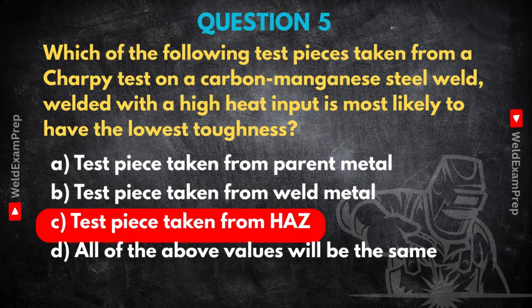The parent metal, away from the weld, keeps its original properties, more or less. And the weld metal itself, if the procedure and consumables are right, might be okay. But that HAZ is often the weakest link toughness-wise when you use high heat input. That's why controlling heat input is so critical. That's fascinating. So the act of welding itself fundamentally changes the material right next to it, and not always for the better if you're not careful.